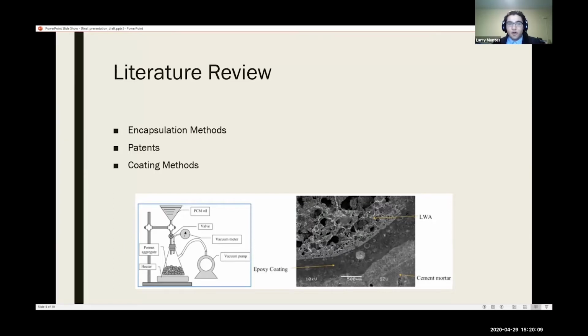Finally, we researched coating methods for the aggregate embedded with PCM, since in liquid state, the PCM will leak out. The most prominent coating methods included immersing the PCM in the aggregate into epoxy, and adding graphite at 15% by weight to the epoxy showed a noticeable increase in thermal conductivity. And another benefit of epoxy coating is that it increases the PCM's resistance to changing shape when the concrete experiences any strain.